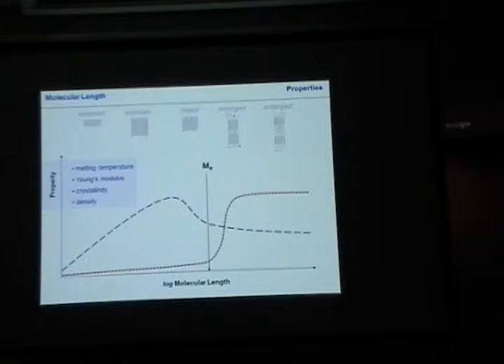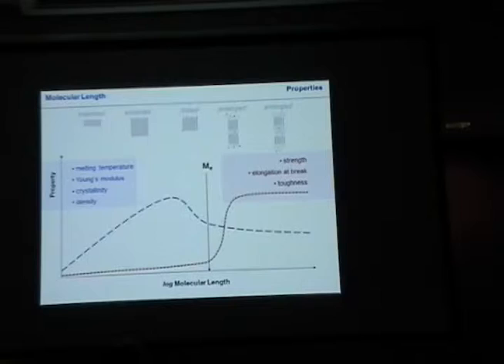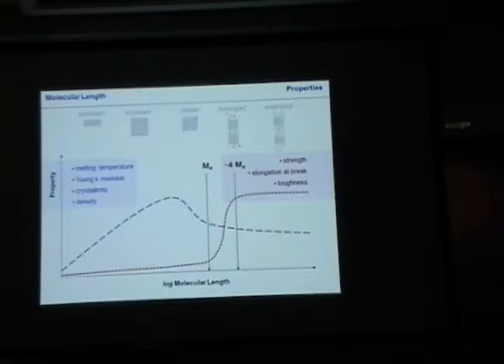The other trend depends on interconnectivity — these entanglements. They are actually very bad, as the little movie on stretching small molecular weight spaghetti showed. Once you have entanglements, these properties actually massively increase very fast and then level off. So that's true for strength, toughness, but I'll also show you that field effect mobility as measured in a transistor will follow this trend.